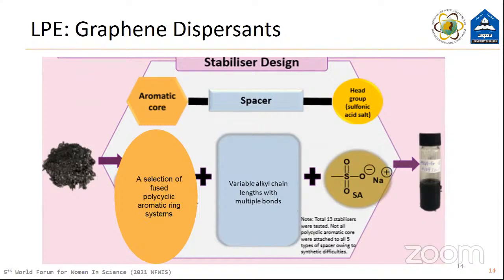Within the library, the nature of the adsorption platform, which is the aromatic footprint, and the spacer between the aromatic footprint and the head group were modified in a systematic fashion. Stronger adsorption onto graphene could increase the dispersion stability, which has the potential to improve concentration as well as the lifetime of the resultant aqueous graphene dispersion. Therefore, the substrates were designed to incorporate different aromatic rings, where we included triphenylene, pyrene, and perylene, and then we used variable alkyl and alkyne chain lengths, so the chain length and nature were also variable in our module. And the head group is the same. We keep using the sulfonate group because it gave us a lot of good results.